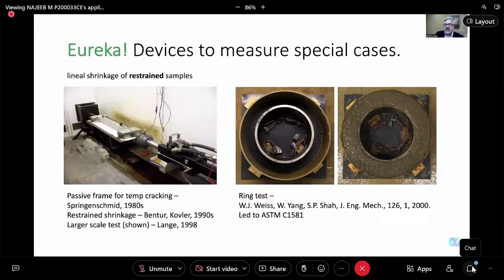Another eureka moment is in development of what's known as the ring test. This is a fairly common test now today. Jason Weiss developed this during his PhD at Northwestern, and it was basically just a case of taking a steel ring, casting concrete around that ring, and then once that concrete is cured, allowing that to age with time, and the shrinkage of the concrete would compress on that steel. And believe it or not, you can put strain gauges on that steel and you can sense how much stress is being applied by the concrete. It's sensitive enough that you can just feel that and then clearly see when any cracks form.